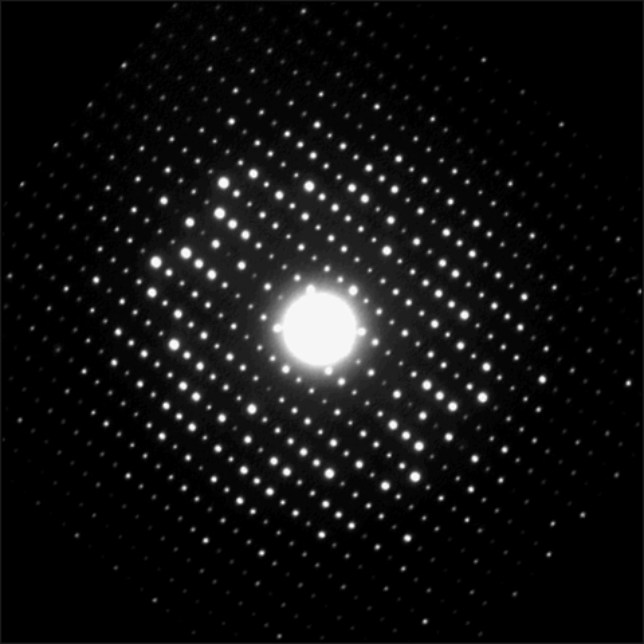Recent progress for structure analysis by ED was made by introducing the Vincent-Midgley precession technique for recording electron diffraction patterns. The thereby obtained intensities are usually much closer to the kinematical intensities, so that even structures can be determined that are out of range when processing conventional selected area electron diffraction data.